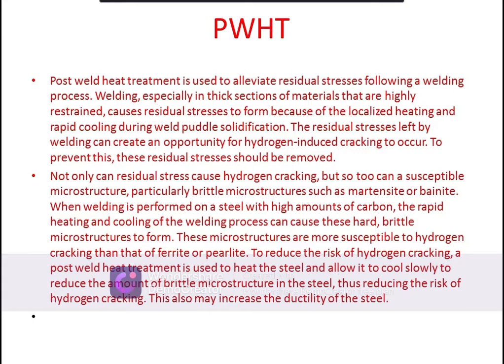Another reason why we are doing PWHT: due to sudden heating and cooling, the hydrogen which is formed during welding will be stuck inside the weld. The hydrogen formed inside the weld will take some time to come outside from the weld. So if the welded area is cooled very fast, it will be stuck inside, and there will be a formation of hydrogen disc crack. To avoid that, after welding we are doing PWHT. If you are doing the PWHT, the hydrogen which is entrapped inside the welded area is able to come outside from the weld. That is also a benefit.